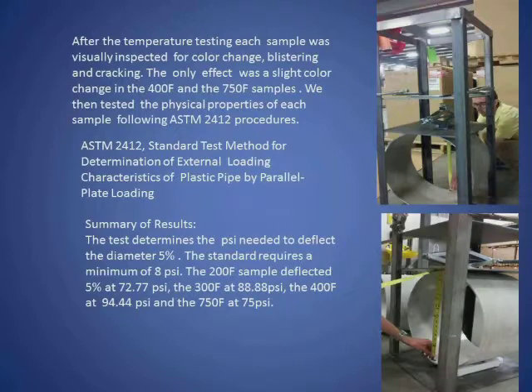After we ran the temperature testing, we visually inspected the samples for color change, blistering, cracking. The only effect was a slight color change in the 400 degree and the 750 samples. We then tested the physical properties, again running it through the 2412 procedures. The name of the test is Standard Test Method for Determining the External Loading Characteristics of Plastic Pipe by Parallel Plate Loading. If you look at the right, this is our apparatus, where we're pressing the pipe down. The test determines the PSI needed to deflect the diameter 5%.